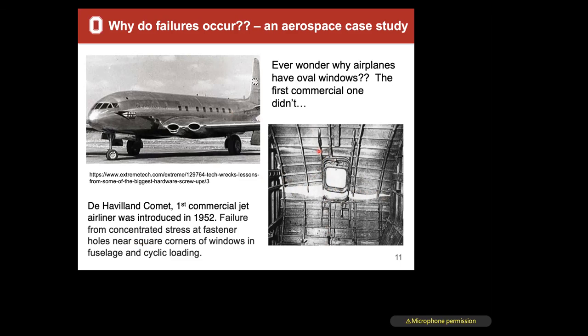Those square windows, along with the fastener holes very nearby, caused a fatigue issue in this aircraft. Fatigue means basically you load something and then you let it go. I put stress on it and let it go. Every time that fuselage would pressurize to go up into flight, and then depressurize when it came back down, that's a fatigue cycle. About 1,000 of those was enough to cause this plane to break apart, and no one had really considered that being the case.